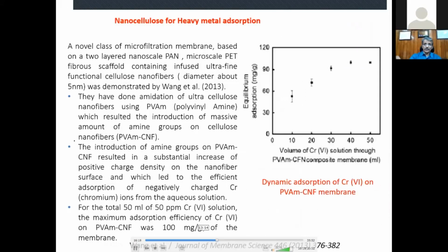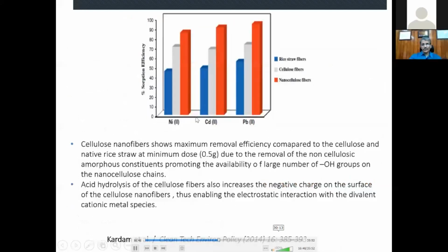seawater could be purified. Dear friends, we can remove nickel, we can remove chromium, we can remove lead. We want to remove chromium 6, which is negatively charged. What you do is you do a small chemistry. You react the nanocellulose surface with polyvinylamine. Once you react with the polyvinylamine, you introduce positive charge on the surface of nanocellulose, and you can see the removal of chromium 6. You can remove nickel, cadmium, lead. So dear friends, we can remove different types of metallic impurities from water.